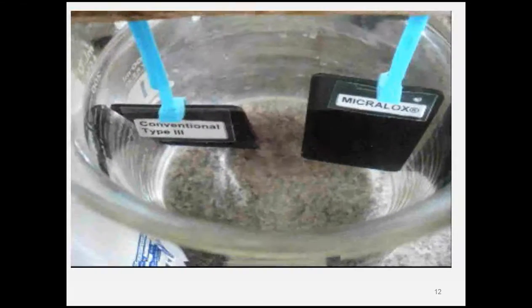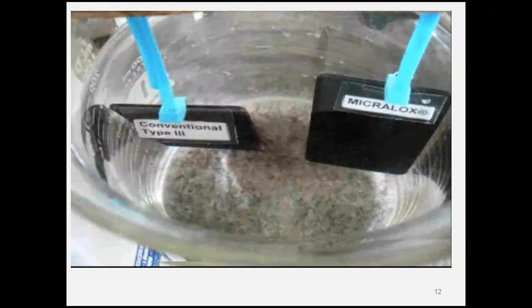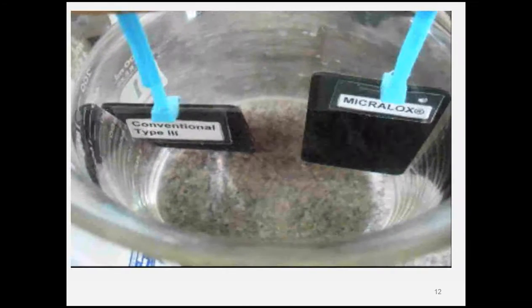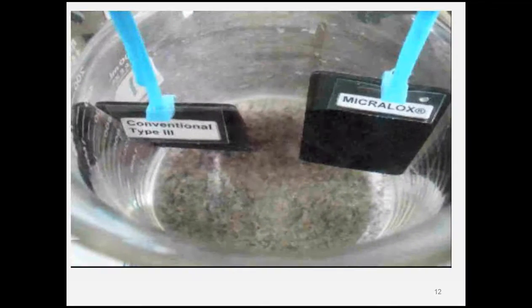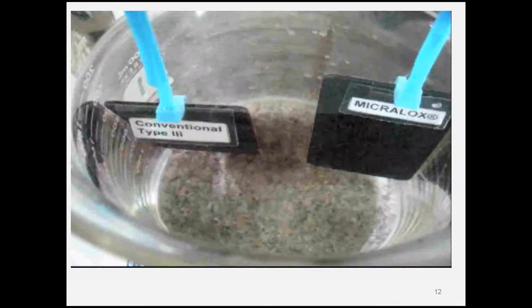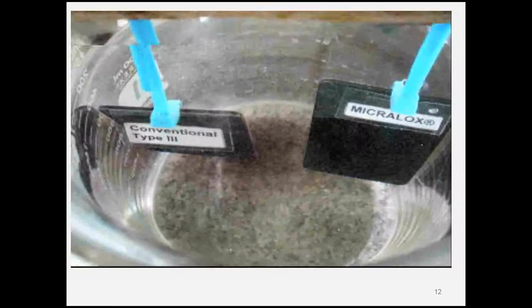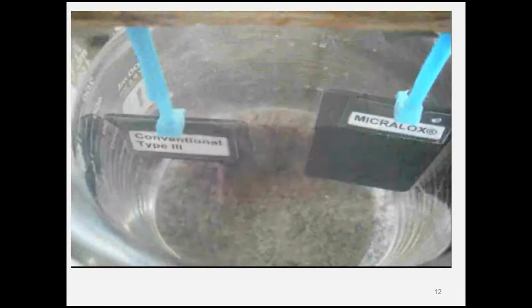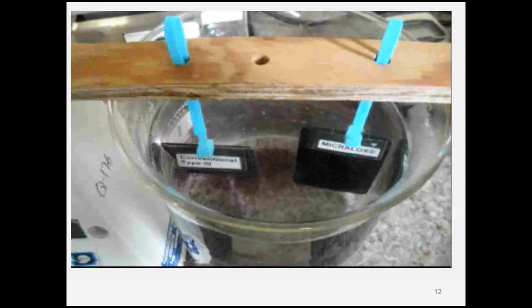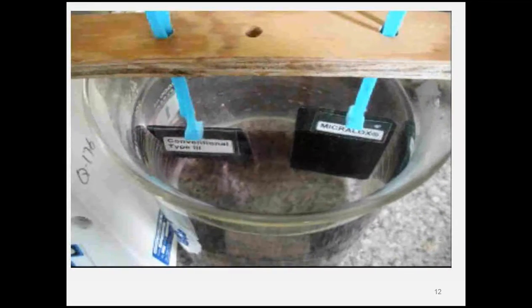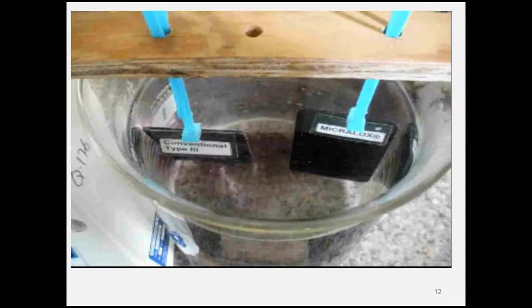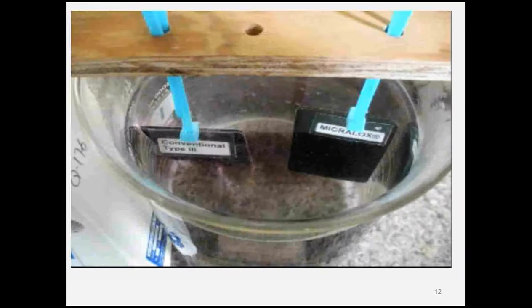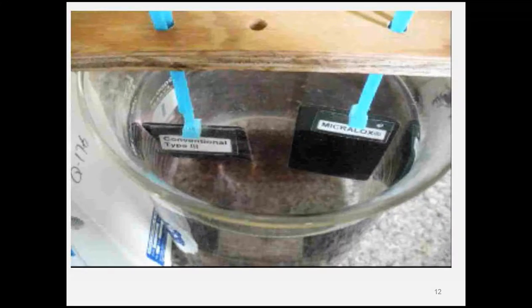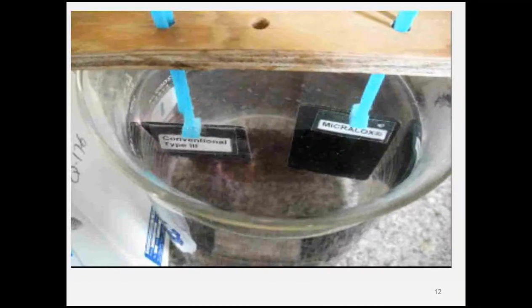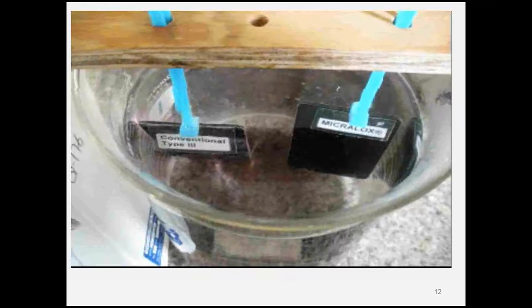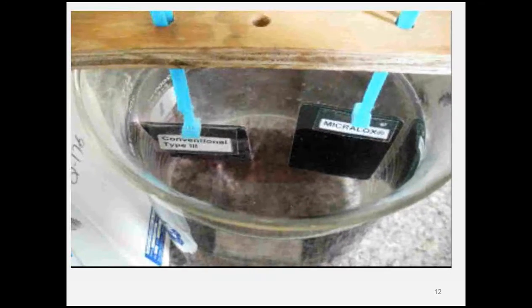So we have a conventional type 3 coating and a MICRALOX panel that has just entered this solution. Almost immediately you can see some gassing or hydrogen bubbles coming off of the piece on the left. If you look close, you might even see some discoloration, some blackish or purplish looking solution. This is the black dye actually coming out of the pores as that anodic coating begins to be attacked.